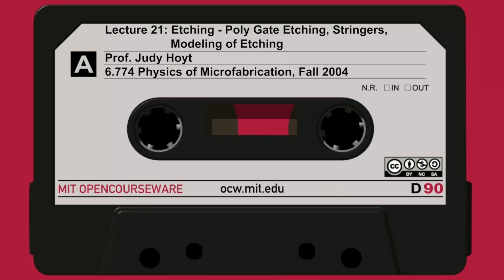They have some indications here also of what the upper electrode might be made of. It seems to be metal. The dielectric material, people are talking about using high Ks. Again, you're trying to store a fair amount of charge in a small space. You can do that with a higher dielectric constant. The bottom electrode could be a combination of silicon and metals as well. So this gives you an idea of what kind of trenches one needs to etch, and this increase in the aspect ratio is pretty amazing in terms of what technology requirements are going to be imposed on advanced etching techniques.